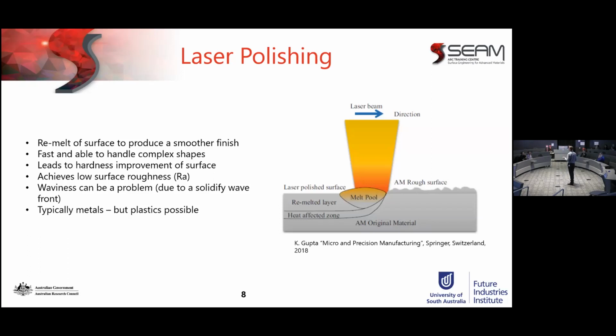Again, you're remelting it, so you can create a heating and cooling cycle. That can lead to hardness improvements. However, one drawback is, I guess, it's a welding process. You may have some sort of waviness occurring. So you might get short range roughness improvement, but your long range roughness may still be set.